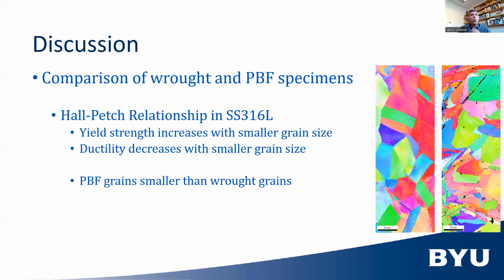And this falls right in line with what we'd expect with the Hall-Petch relationship, which in general says that yield strength will increase in a material as we get smaller grain size, and that correspondingly ductility will decrease with the smaller grain size because we don't have as much slip between the grain boundaries. So this matches exactly what we found, that the PBF grains were smaller than the wrought grains, and it showed that same increase in strength and decrease in ductility.